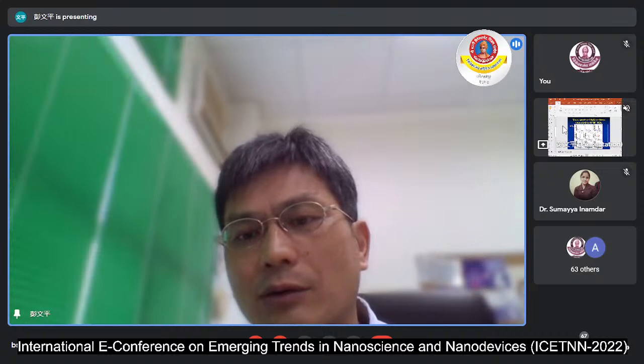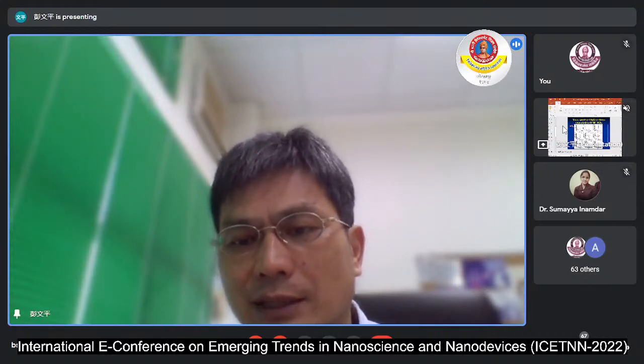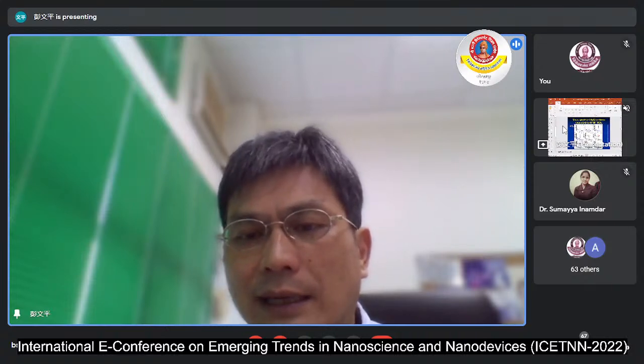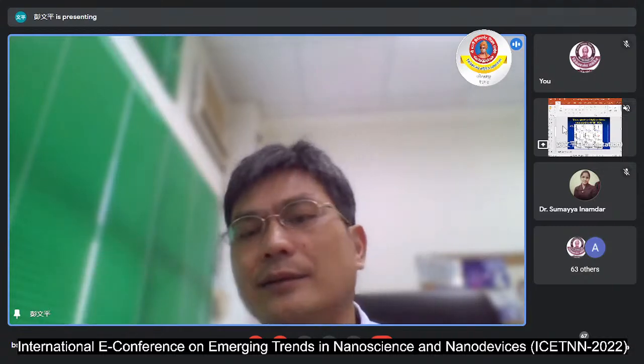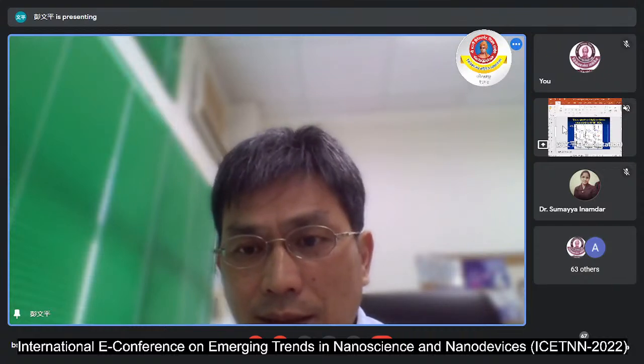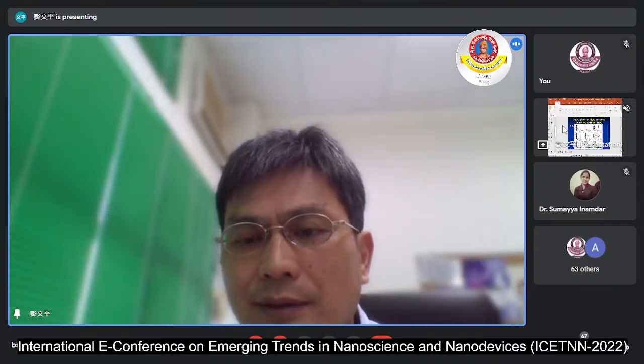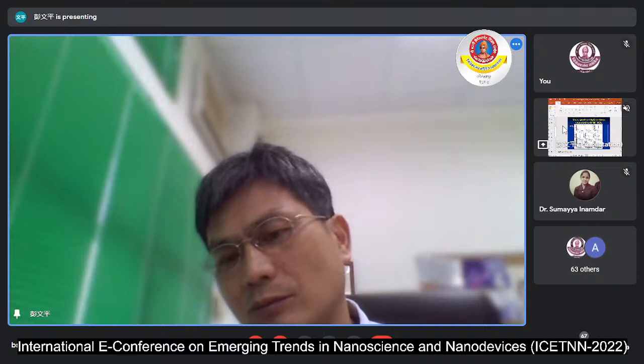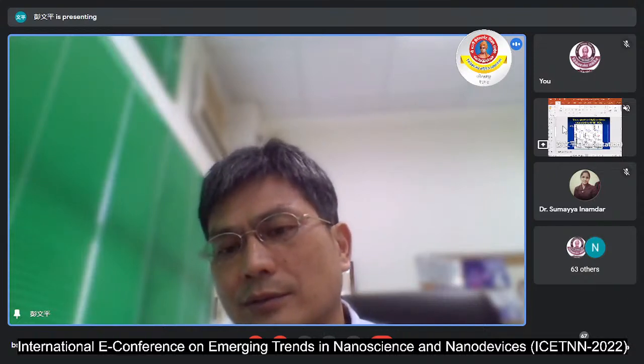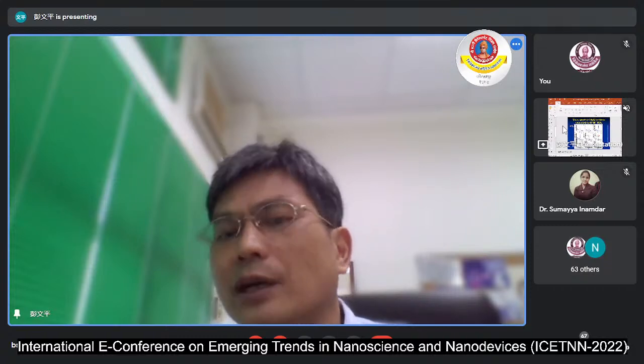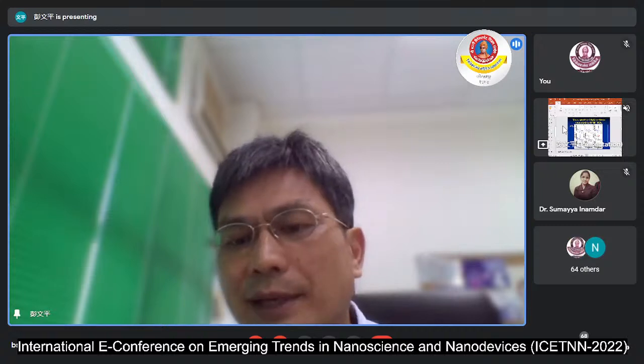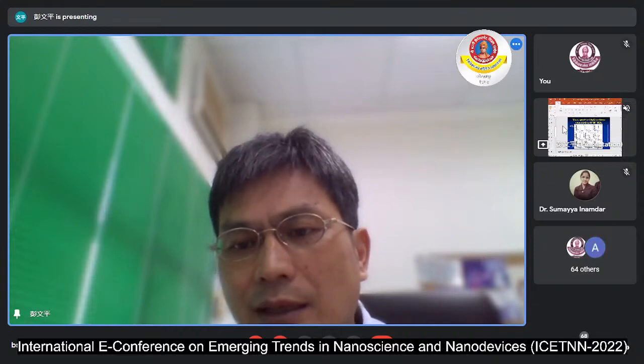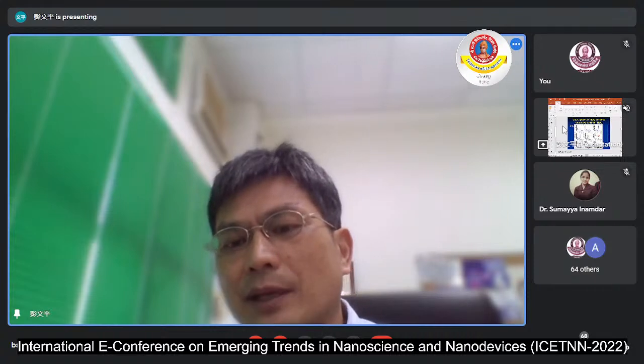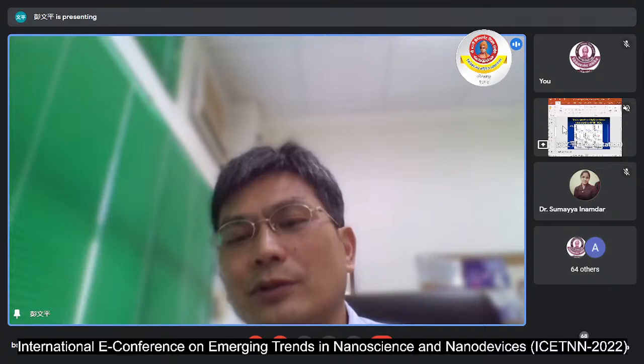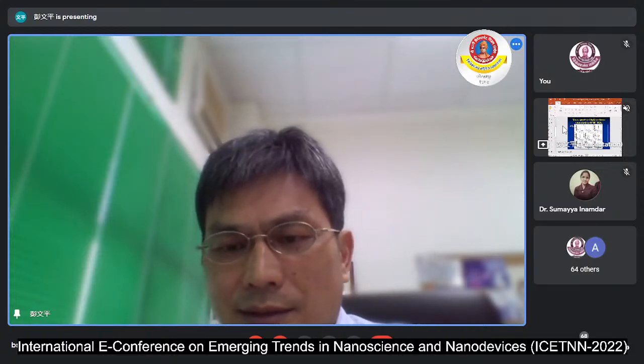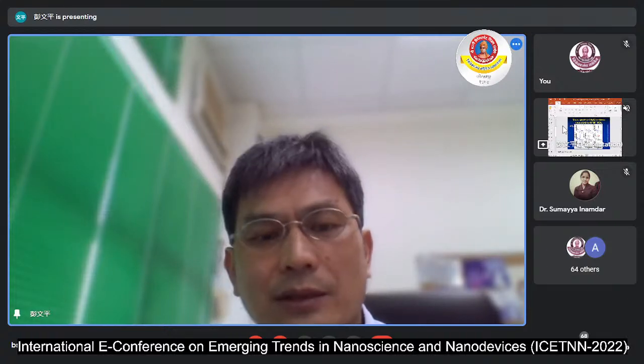And then we know our signal is quite stable, so we can change the concentration and observe the signal. The blue one is where we just put diamond in and see the signal. As you can see in the figure, the red one is the second injection: after the diamond injection, we take the residual solution, use another nanodiamond, and inject again. We can still see the signal. That means at a higher concentration, in figure E, you start to see more signal. The first diamond took up the protein, but there are still residual IgG molecules inside the solution, so we start to get signal. This is what we call the second injection.